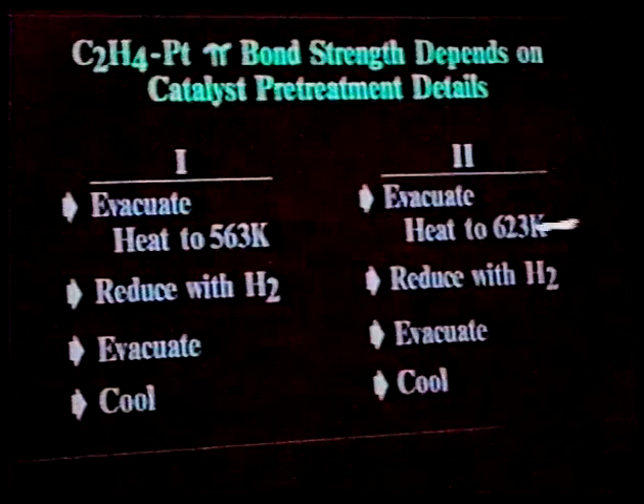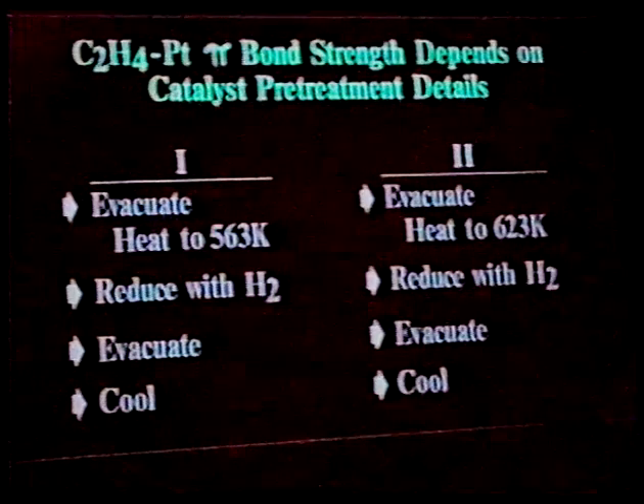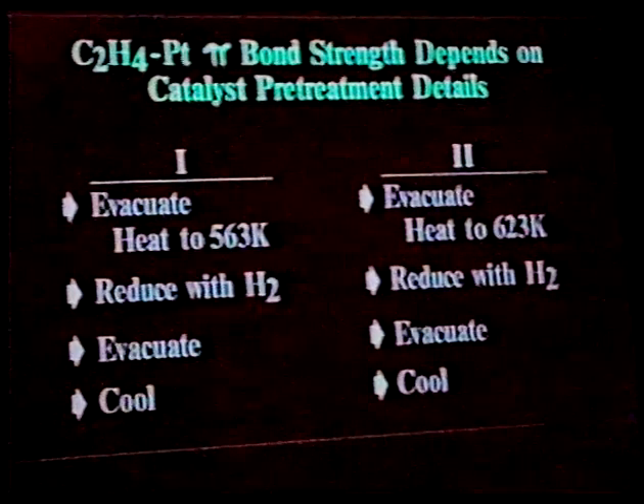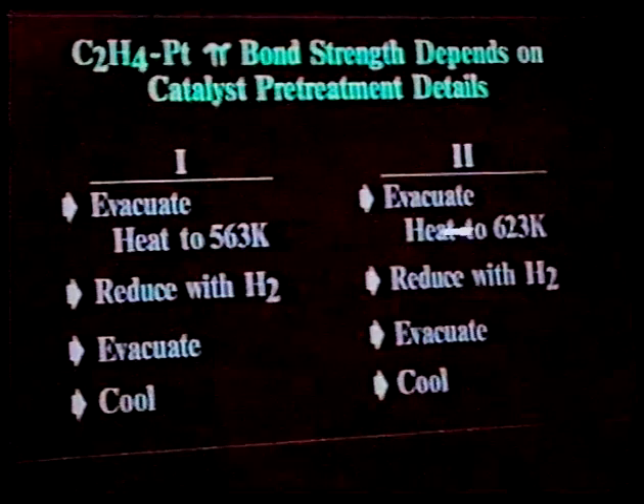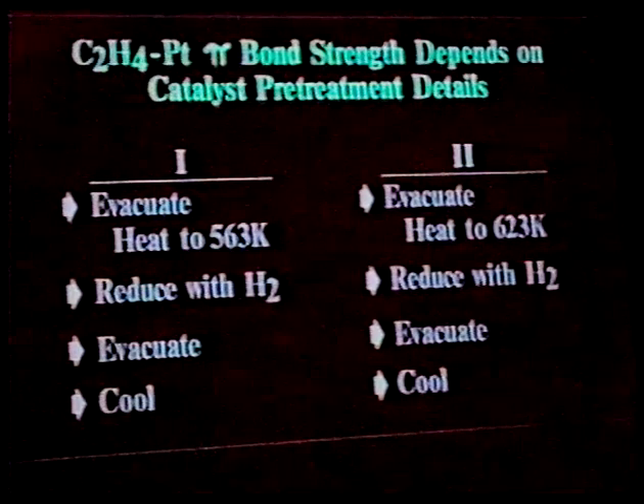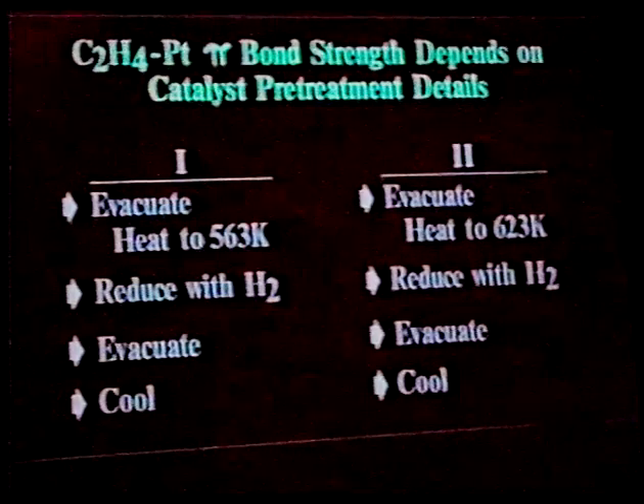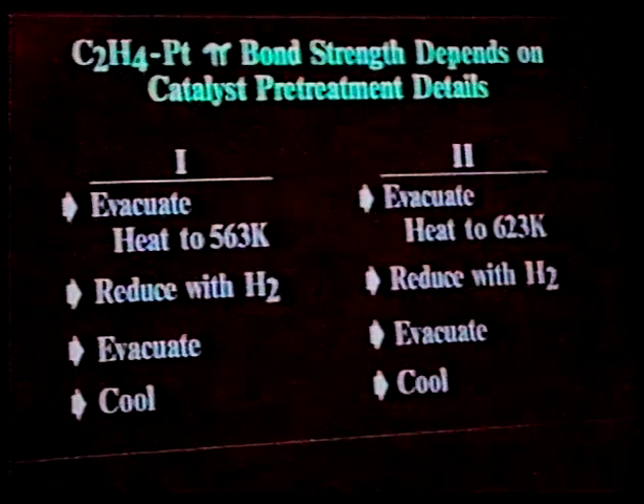Alternatively, you can heat to a slightly higher temperature. And then you can go through exactly the same sequence of steps, so that the only real difference here is the temperature to which the catalyst is heated prior to the exposure to hydrogen, and consequently the temperature at which the evacuation is being done.